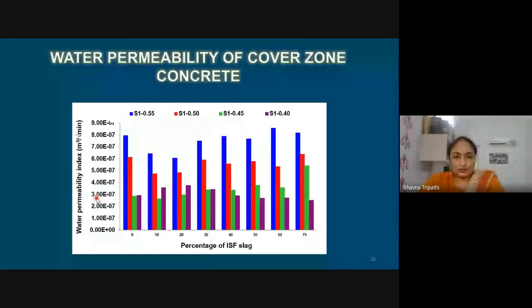Another test which we had performed for permeability was the water permeability of cover zone concrete. Again, the Autoclam permeability apparatus was used, and here also we can see the concrete specimens which have more than 0.45 water cement ratio, that is 0.50 and 0.55 water cement ratio, both these mixes had higher permeability.